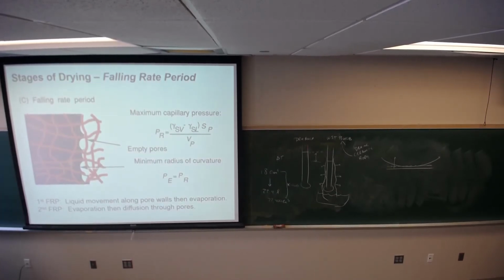okay? And that shrinkage process, we don't have this network per se. We have a bunch of particles forming this network. So this cartoon version doesn't do very well for us because we start thinking of this as having pore channels, but what you actually have is a bunch of particles with basically space in between them, and you can argue for pore channels, but they're not well defined. They are essentially this tortuous path of water through a pore system.